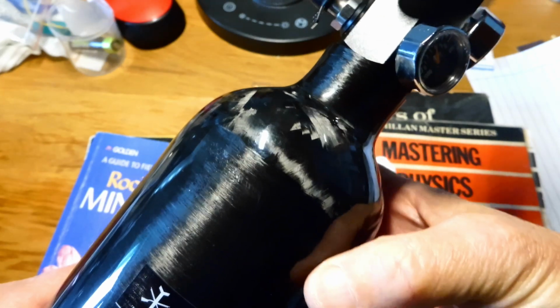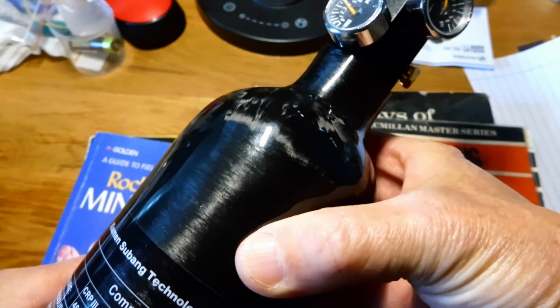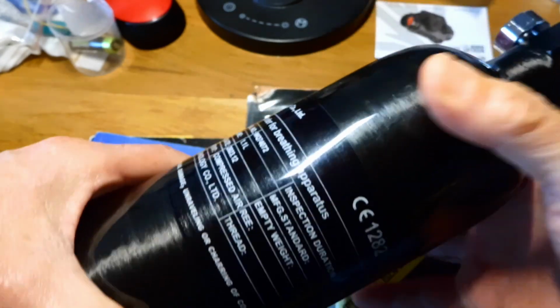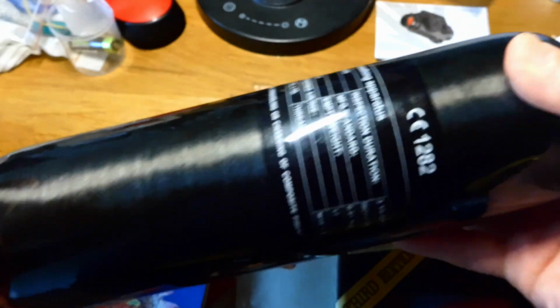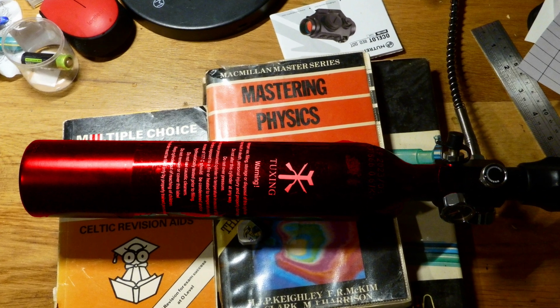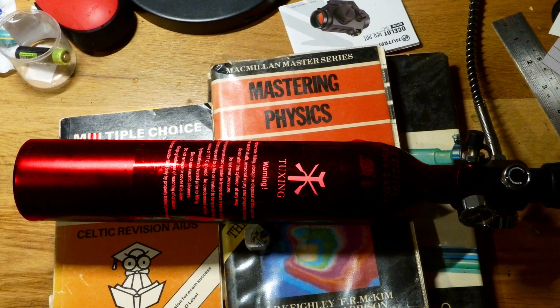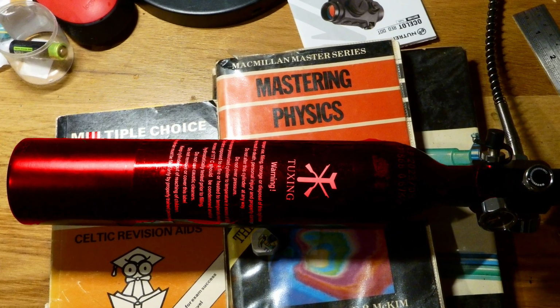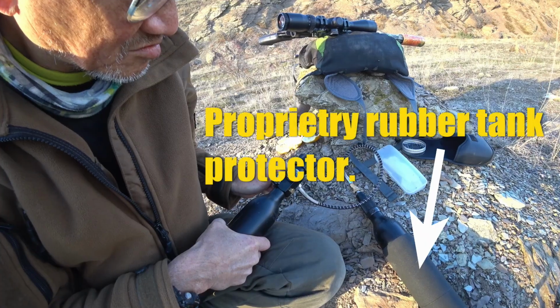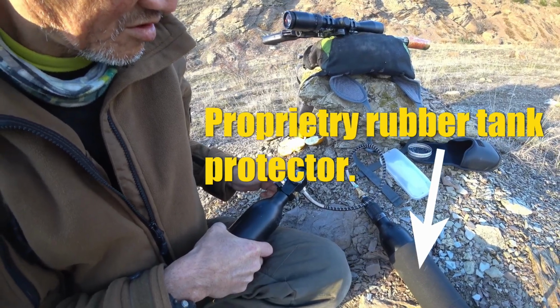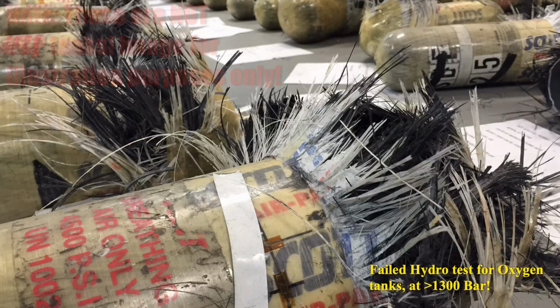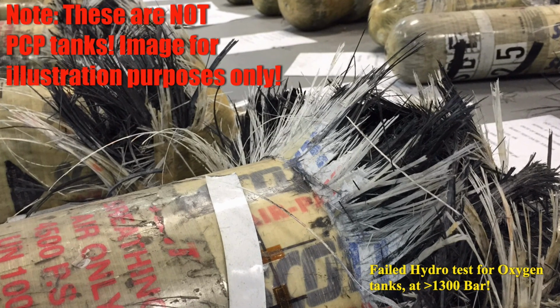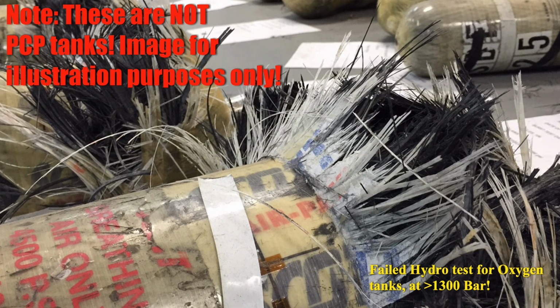The carbon fiber bottle is even prone to physical damage, due to the softer nature of the coating epoxy resin versus the aluminum surface. Most aluminium bottles will not be hard anodized but rather painted in order to reduce the cost of production. Exterior physical damage. Small scratches or dents may have no long-term effects on the integrity of an aluminum cylinder, however similar amounts of physical damage to a carbon fiber tank may render it no longer serviceable, or drastically reduce its lifespan.